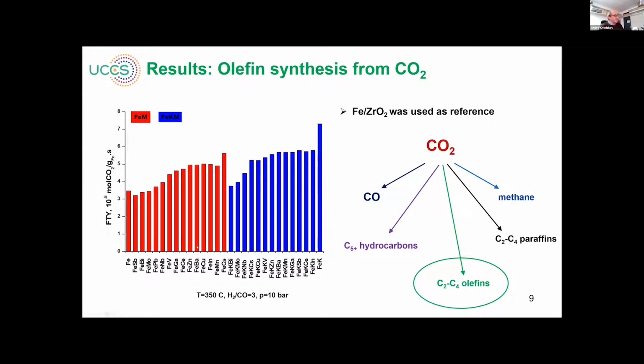So this is the activity results which we obtained. What we can see here is that the most significant increase in activity comes when we add potassium as promoter. Similar results, but slightly smaller, with cesium, so basically these alkaline metals. However, for other elements, there is some modification of activity, but the effect is not so significant. But what was most interesting for us is not even the activity, but the selectivity.